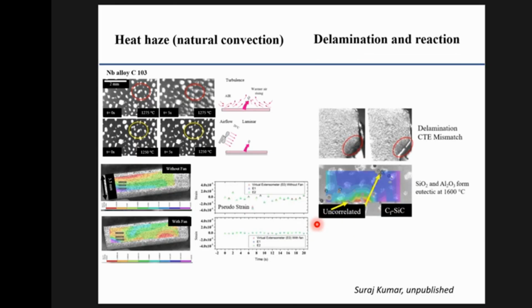The last, of course, is delamination and reaction. We used alumina, and in one case, there was a surface layer of silica, and the alumina and silica react. There's not a whole lot you can do about this, except you have to be sensitive to the paint that you use, depending on the sample that you have.